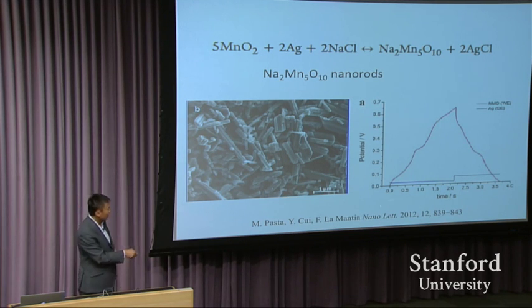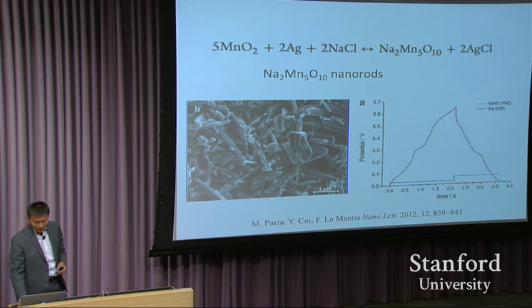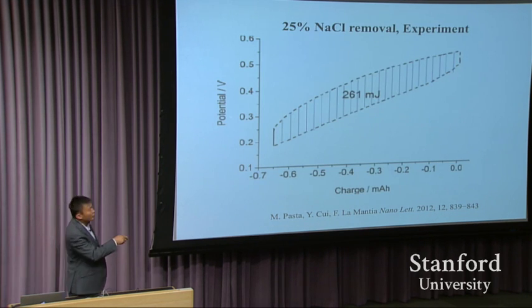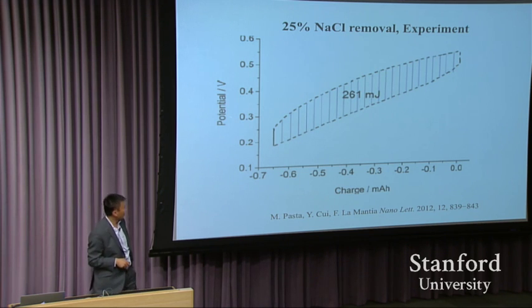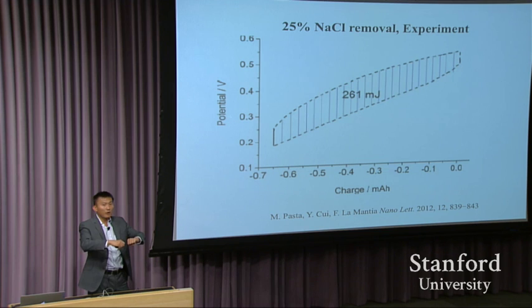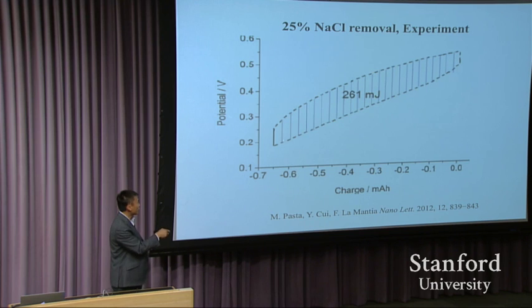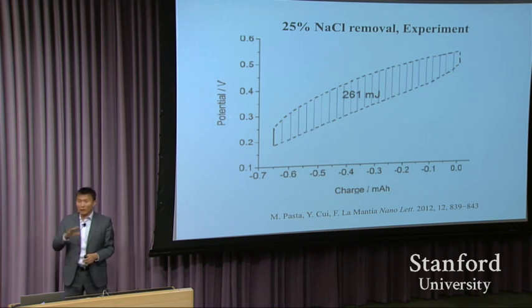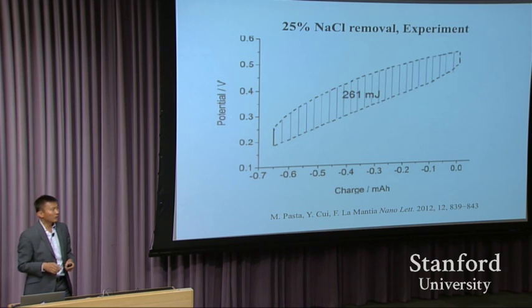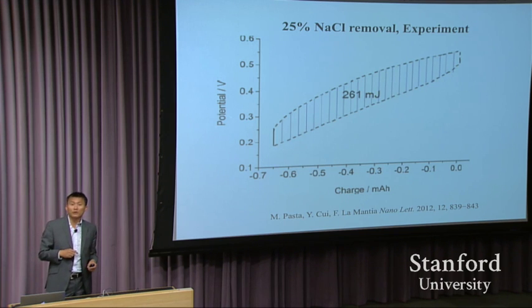And to give you an idea, when you put in charges, how the voltage responds to this current charging and discharging process. This is experimental data. We measure the potential. We measure the voltage between the two electrodes. Now you start step 1, discharge, take out the sodium and chlorine from seawater, put them into your electrode, and you take out the fresh water and put in seawater and charge it, and now come back and change it back to seawater. This is 261 millijoules of energy we put in, just by measuring these areas. And this is for a very small device. Using this energy, we actually take out roughly 25% of the sodium chloride from the seawater. So indeed, this is the real seawater we did the experiment on, from Half Moon Bay.